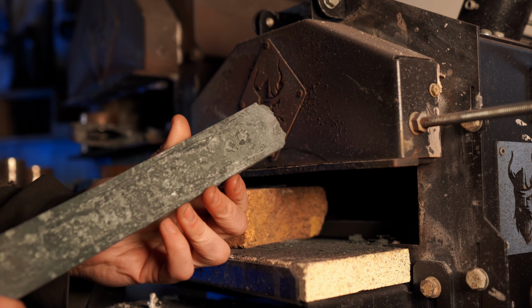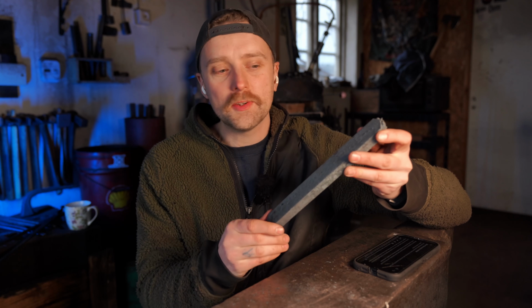So I left the billet in the forge to cool down very slowly, and I do that to anneal it and make it a little bit softer. Because I'm going to try something that I've never done before, and that is to make what's usually referred to as raindrop pattern Damascus, or pattern welded steel.